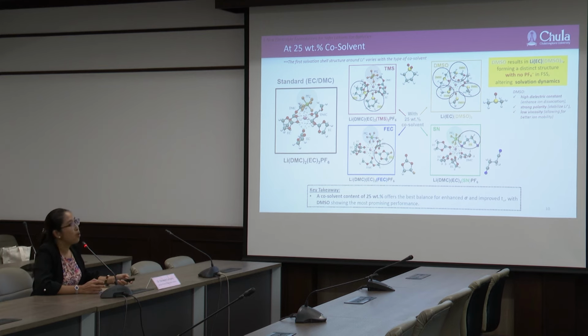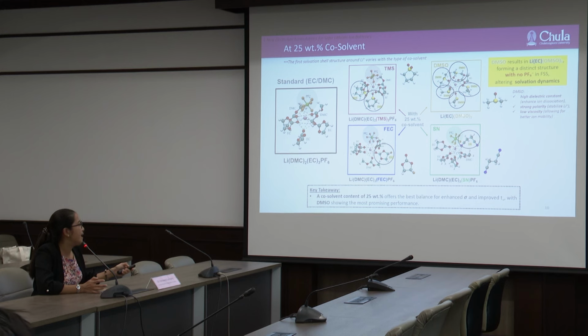At 25% co-solvent, the first solvation shell around lithium ion varies with types of co-solvent, and DMSO results in lithium ion coordinating with 1 EC and 5 DMSO. This forms a distinct structure with no PF6 anion in the first solvation shell, and this structure can alter the solvation dynamics. So the key takeaway of this study is that 25% of co-solvent offers the best performance for enhanced ionic conductivity and can improve the lithium ion transference number, with DMSO showing the most promising performance.